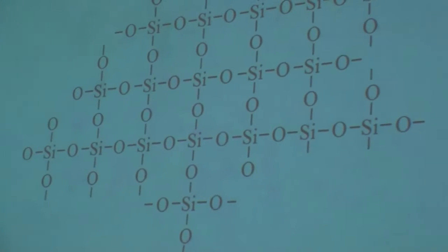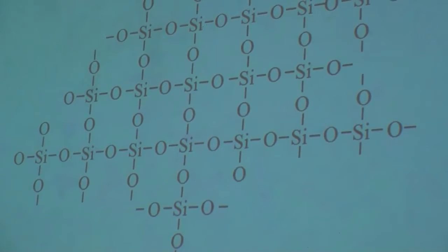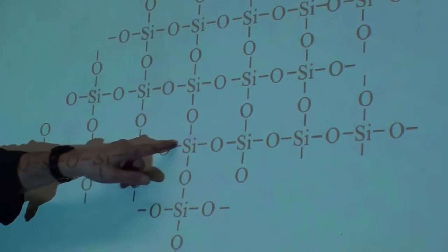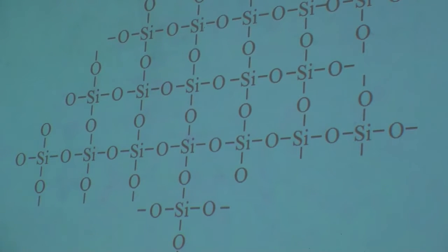This is your structure of silica. Every silicon is at the center of a tetrahedron. It's not planar, these are three dimensions. The four oxygens are very strongly directed towards the corners of a tetrahedron. The angles here are the tetrahedral angle, 109 degrees, and that can't change because otherwise the energy goes way, way up. So it's a very rigid network. These are called your oxygen bridges, and this is a very highly viscous, non-ionic, gooey material with a network.